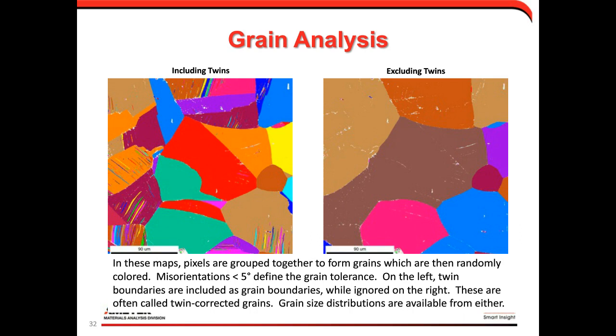But as we go through this grain grouping approach, the other thing we can do is to say if the misorientation matches a specific relationship, so in this case a twin relationship, which would be a 60-degree rotation about a 1-1-1 crystallographic axis for the primary sigma-3 twin, we'll say let's take that specific type of boundary and ignore it when we're calculating our grains. And when we do that, we get a different grain structure shown on the right where we see our grains where we've excluded the twins, and we see our effective grain size is much larger than if we include the twins. And so one of the nice things about EBSD is we can actually calculate the grain size distributions from either a twin included or a twin excluded defined grain structure.